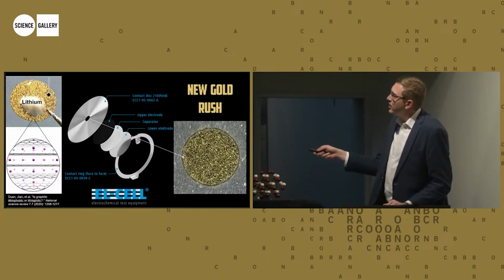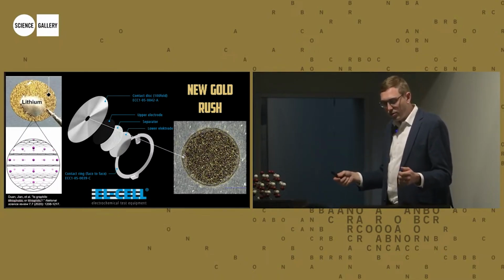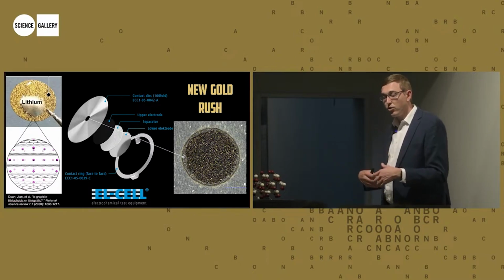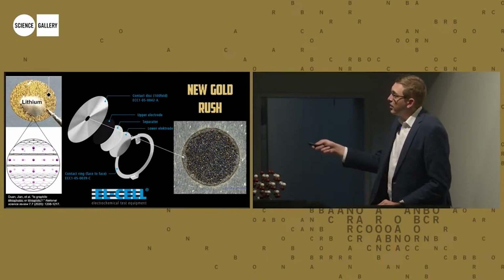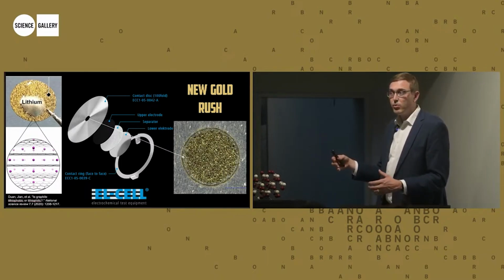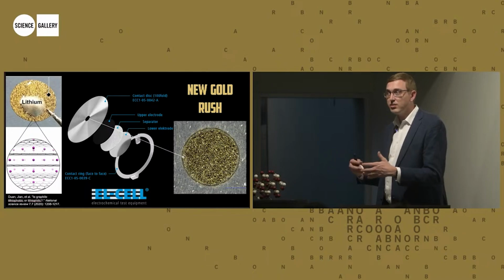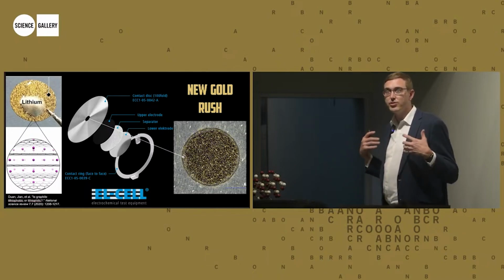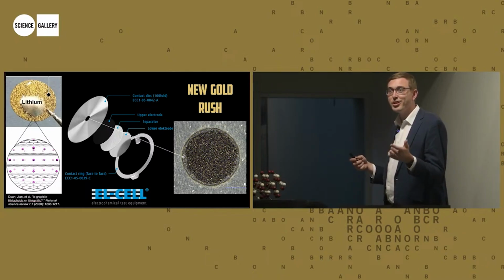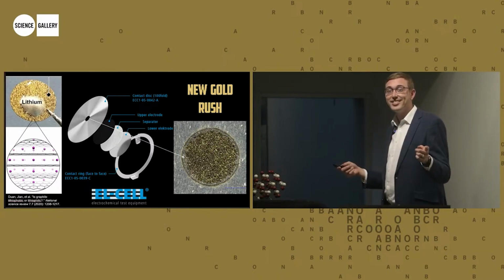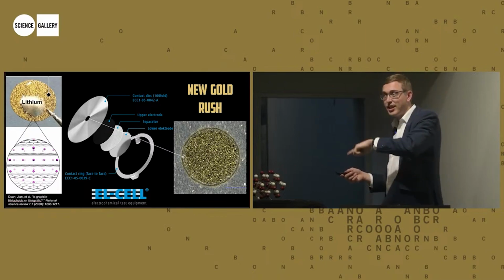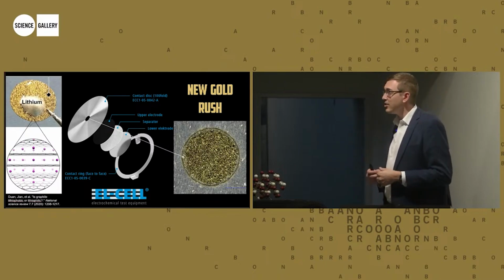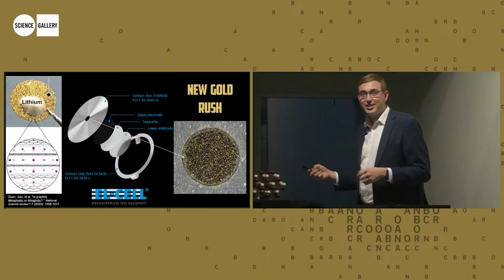Now, what happens when you turn on your phone and you start drawing electrons out of the battery? The lithium is dissolving into the electrolyte, because the lithium wants to dissolve, okay? It's like having a metal inside of some acidic solution. It wants to dissolve. And what happens when it dissolves is it becomes lithium plus. So where does the electron go? It goes into your device, runs all the way around your wires, and then goes onto the metal oxide side. So it's the lithium dissolving into the electrolyte that is giving you electrons to power your battery, okay?